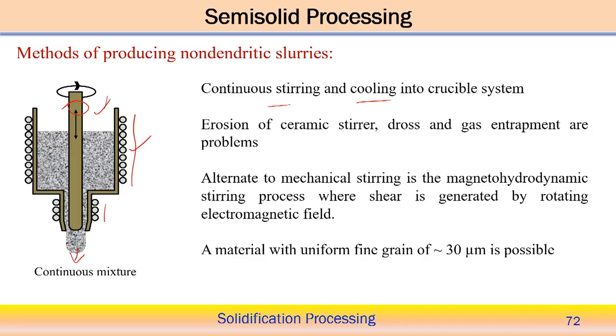You can observe this even in mold casting, where we put in the liquid metal, dross can be created and gas entrapment can occur during the passing of the liquid metal through the channel, the runner and riser, and finally reaching the mold volume or cast volume. So during this process there might be some kind of gas entrapment. Here also, since it is associated with the stirring action, gas entrapment might occur. This is one of the problems associated, and we can use the ceramic stirrer in this case, as we know ceramic stirrers have typical properties.